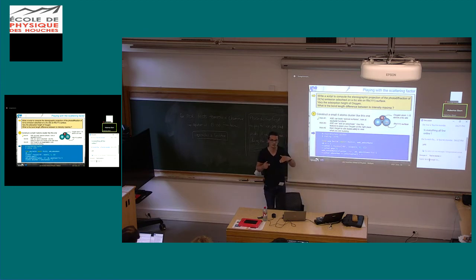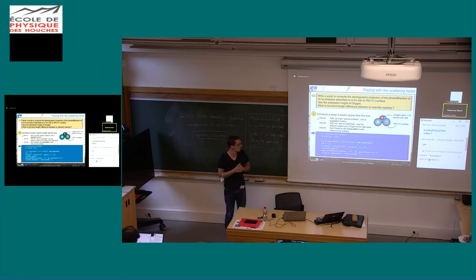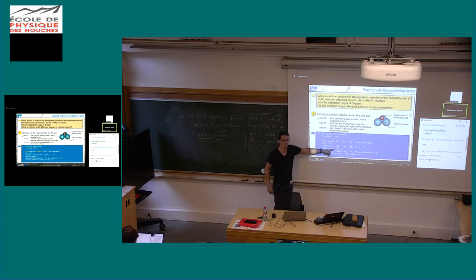So 1 layer, 2 by 2, okay? It will produce 4 atoms, actually, but this is only 3 atoms. If you use cluster.edit or view cluster, you can see that you have to remove the last one. As an atoms object from ASE is just a list, you can just pop the last one, and you will have a cluster of 3 rhodium atoms.